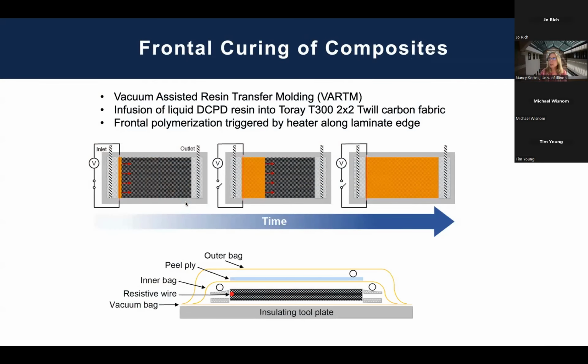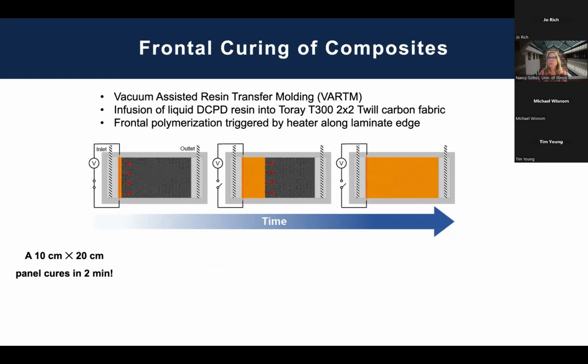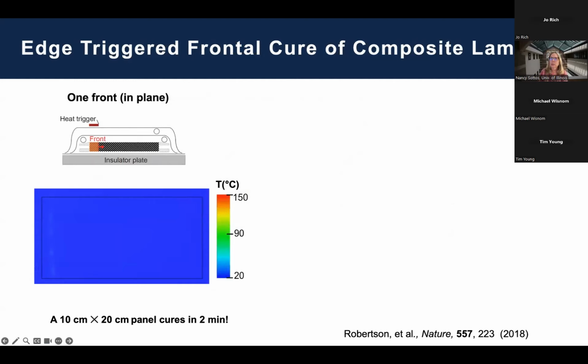So let me tell you about how we've put this into composites. One technique we've been using is vacuum-assisted resin transfer molding, or VARTM for short. Basically, we infuse the resin in. DCPD has a very, very low viscosity, so it's very amenable to things like VARTM. We can use a traditional bagging technique, and the first thing we did was use an edge trigger. And we're able to process a panel very quickly. Let me show you a video of this. It's going to trigger along this left edge. It's in this case a 10 by 20 centimeter panel.